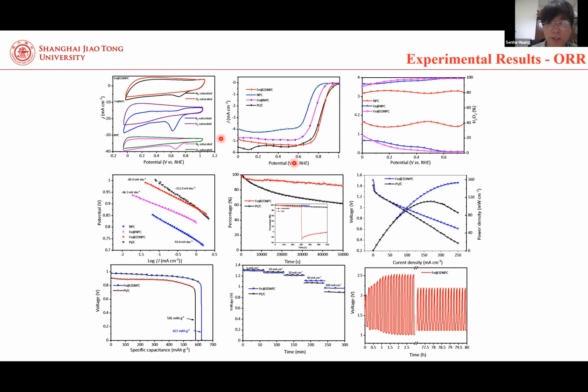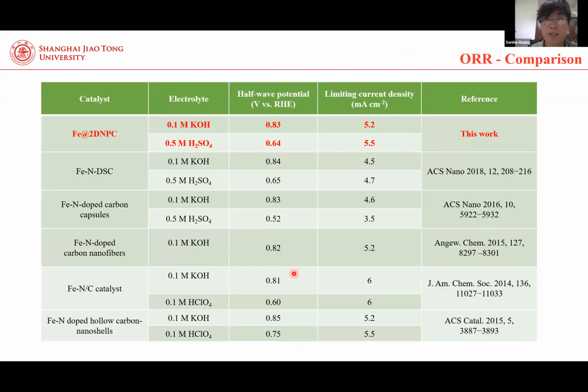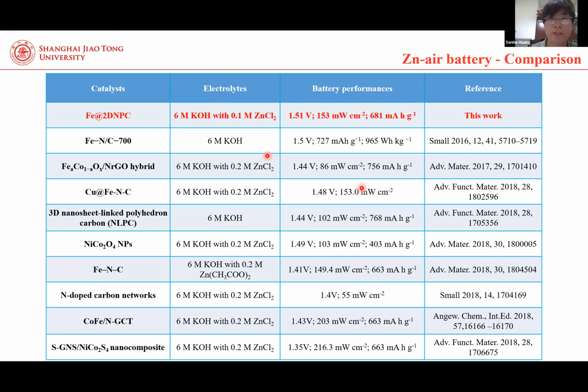Besides, when this catalyst is assembled on the electrode of a zinc air battery, the device also shows a promising performance. Compared with other high efficiency iron-based catalysts, our catalyst almost shows the best oxygen reduction reaction catalytic performance. And also compared with other materials, we can also find a promising performance of our catalyst in zinc air battery.